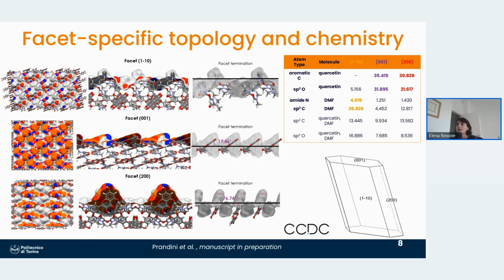And then in different colors, we can also highlight the presence of hydrogen bond donors and acceptors, which are the red and blue parts, and then the aromatic bonds, which are those orange parts. So we can also formally calculate, as you can see here in this table, for each facet, the area occupied by the different types of atoms. So we can see, for example, that this large facet here is very much exposing DMF molecules, while these other two are a little bit more occupied by the aromatic molecules, which, if we look at facet 001 and 200, are in two very different positions.